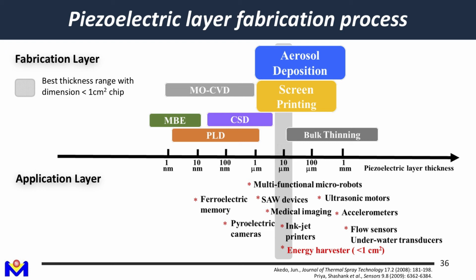I heard from some of my colleagues in the community, you probably will see him in this workshop, that's AE. They are working on pacemaker energy harvesting. They are working with a French company. They can also do this kind of thinning process. And the limitation I heard is around 20 micron, because if the thickness is even thinner, you will have too much imperfection, cracks inside the film. So the overall piezoelectric property will degrade very quickly. Okay, so with this method, you still have certain limitations.